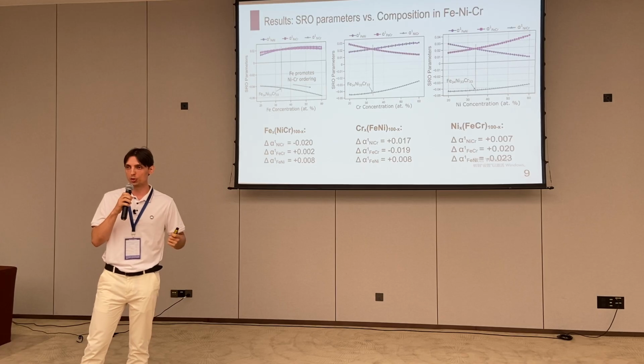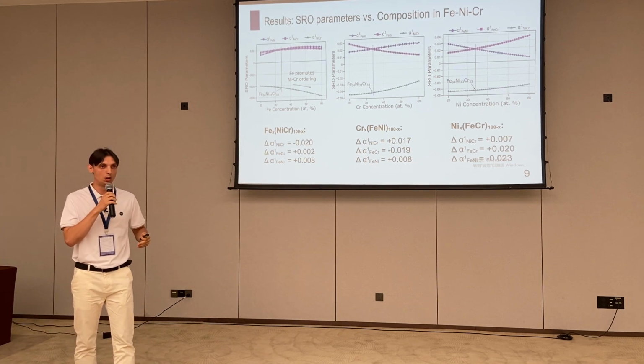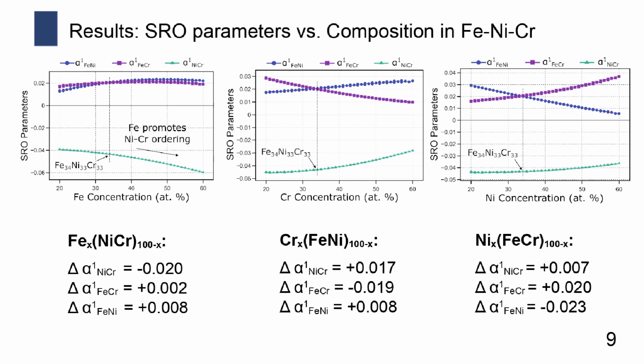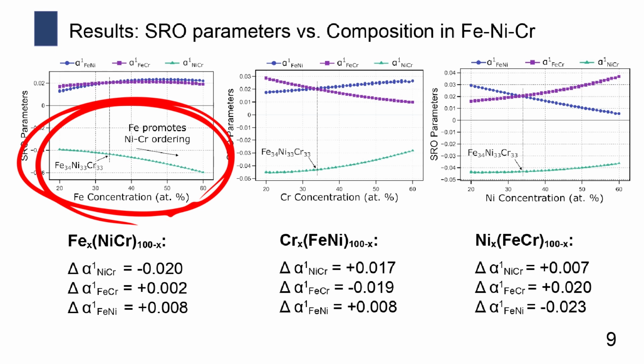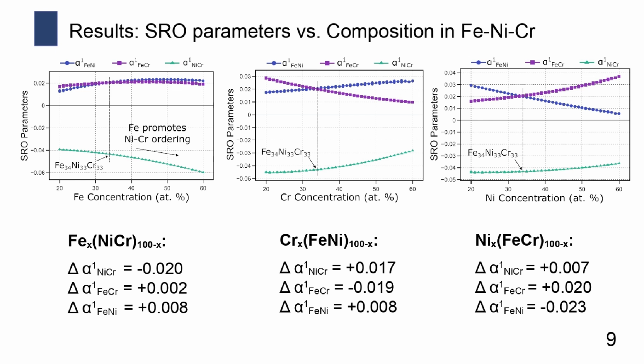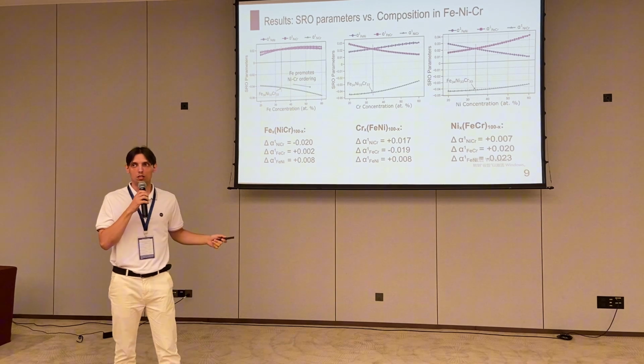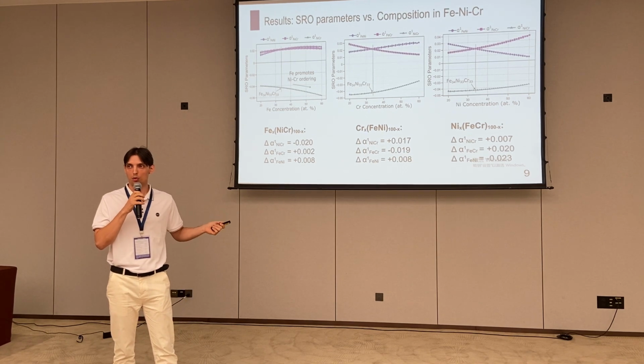The previous slide showed the big picture, and this slide has a more detailed view of how each of the elements influences the short-range order in these systems. And we found an interesting tendency. The more iron is added to the system, the more the tendency for nickel and chromium to come together and order. This is opposite to what we could have expected, because we usually expect that the more an element is added, the more dilution of the property. But addition of iron promotes the ordering of these two elements, nickel and chromium, while adding nickel or chromium separately weakens the strength of ordering for the nickel-chromium pair.